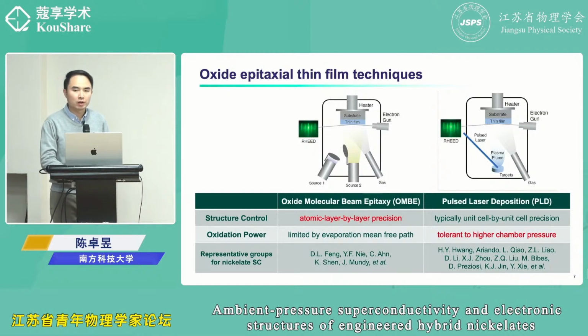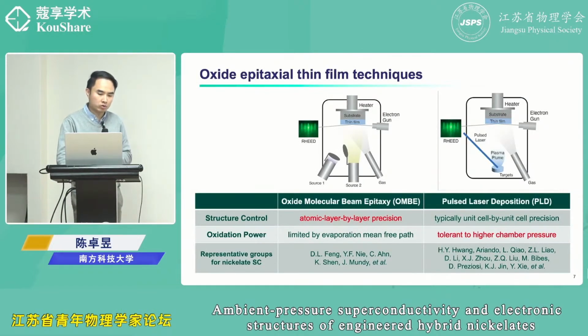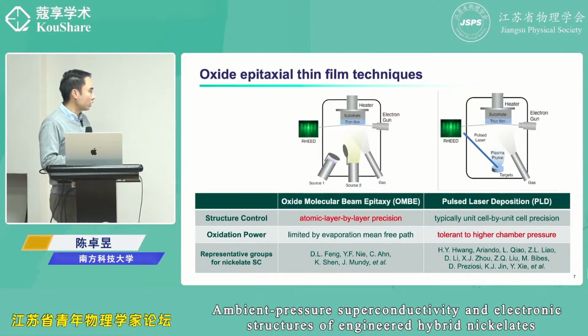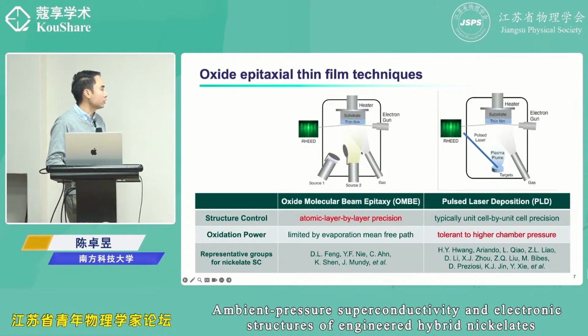There are 2 mainstream oxide epitaxial thin film techniques. The first one is people call oxide molecular beam epitaxy, or OMBE. It has a pretty good structural control precision. It can do deposition atomic layer by layer by using different shutters for different cation sources. But it has a limitation. The chamber pressure for this method cannot be too high. If the chamber pressure is too high, the mean free path of the evaporated material will be shortened, and then nothing is going to deposit on the substrate. So considering the deposition rate, you need to keep the chamber pressure at a pretty low condition.